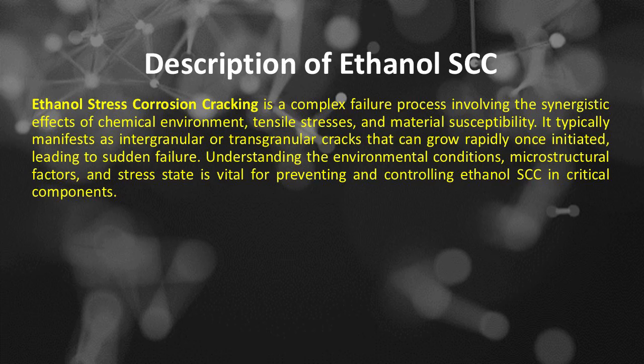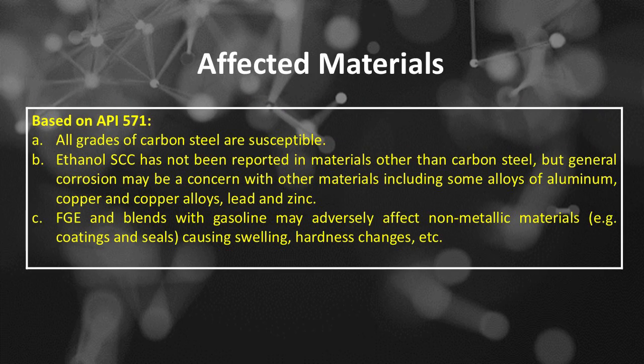critical components. Ethanol stress corrosion cracking affected materials based on API 571: Number A, all grades of carbon steel are susceptible. Number B, ethanol SCC has not been reported in materials other than carbon steel, but general corrosion may be a concern with other materials including some alloys of aluminum, copper and copper alloys, lead and zinc.